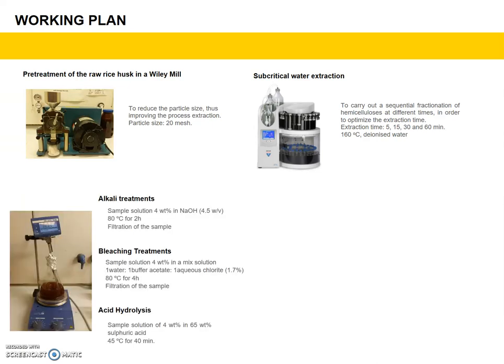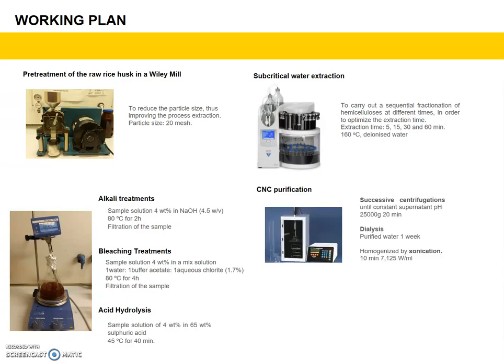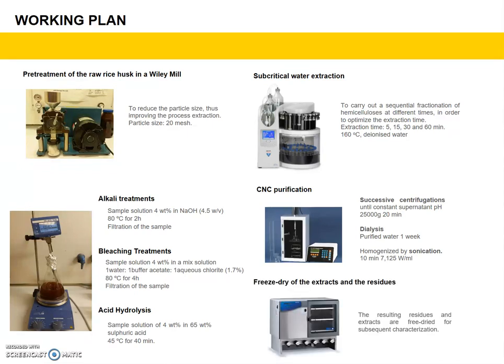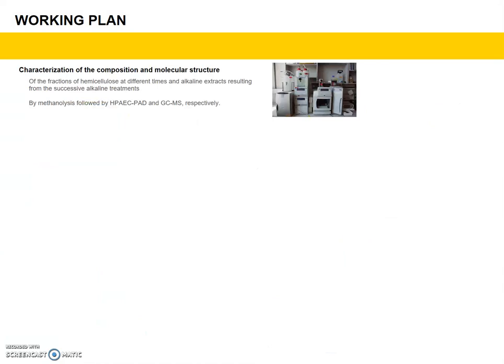On the other hand, the milled rice husk was also submitted to 3 consecutive alkaline extractions, and the resulting residue was also used to continue with the bleaching and acid hydrolysis. After that, the CNC were purified by successive centrifugation and dialyzed during 1 week previous to the sonication. In the same way, the extracts resulting from the alkaline extractions were freeze-dried for subsequent characterization of the composition and molecular structure by high-performance anion exchange chromatography with pulsed amperometric detection, and gas chromatography mass spectrometry.